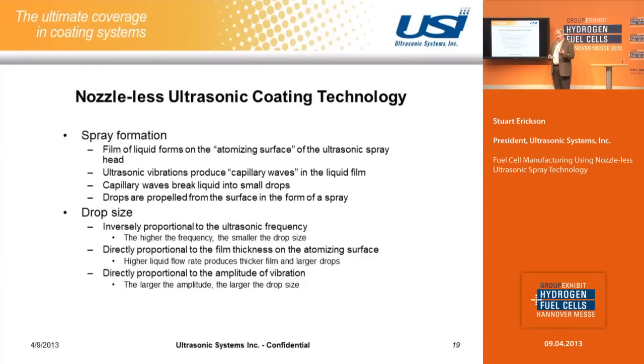So basically the mechanism, and it's a short time period here, so I really can't go into much detail about the exact mechanism of ultrasonic spray. But basically you have a vibrating surface, the atomizing tip of the spray head, what we call the spray forming tip. And we apply the liquid to that tip, and a film of liquid is formed on that vibrating surface. And the ultrasonic energy forms capillary waves in that thin film, and it breaks it up into small drops, and it propels it away from the head in the form of a spray.